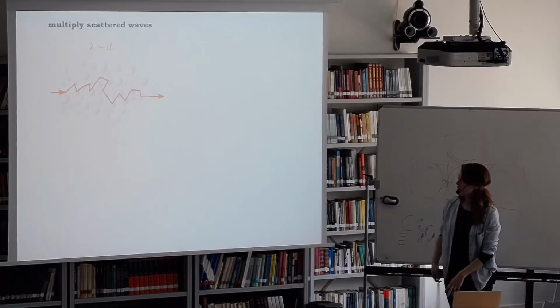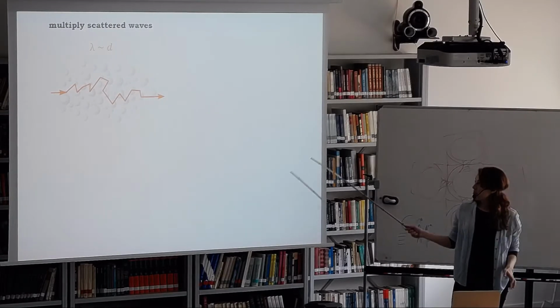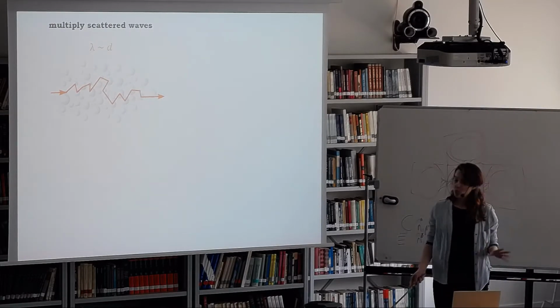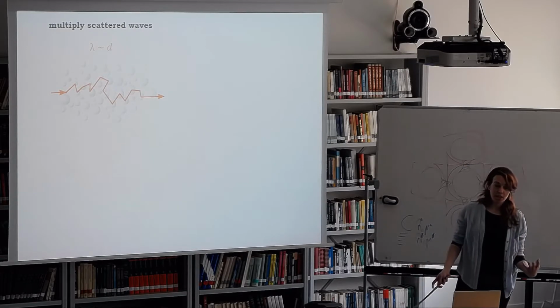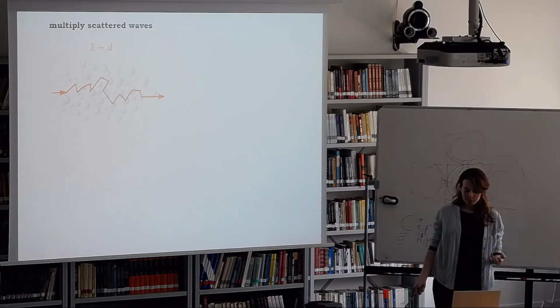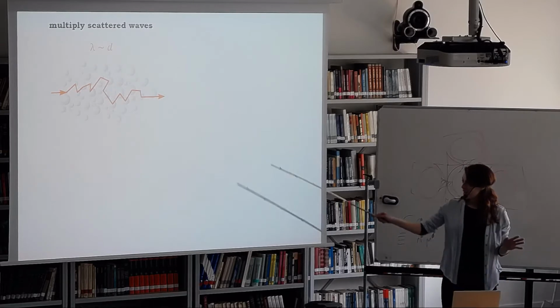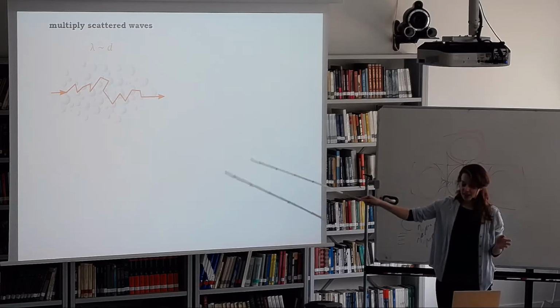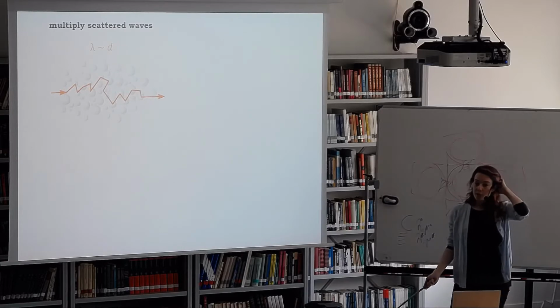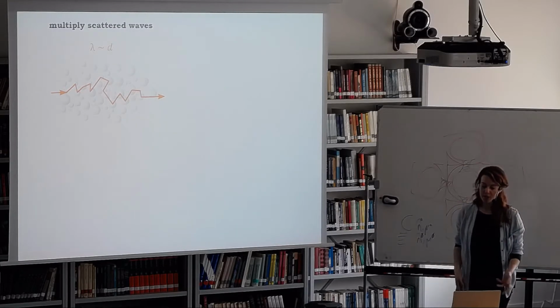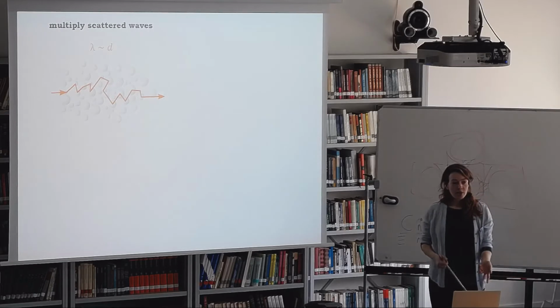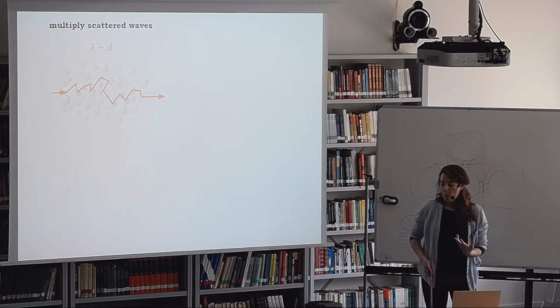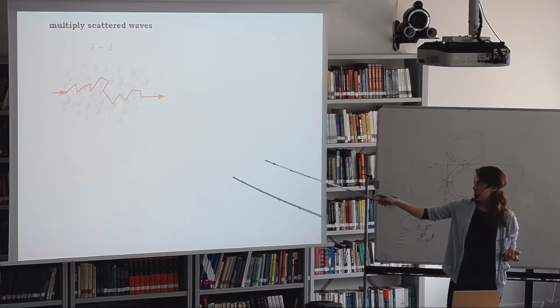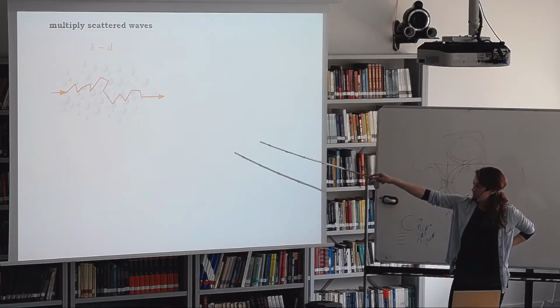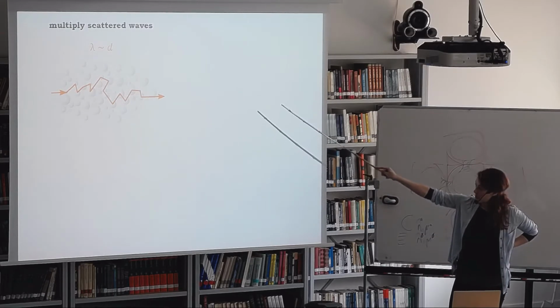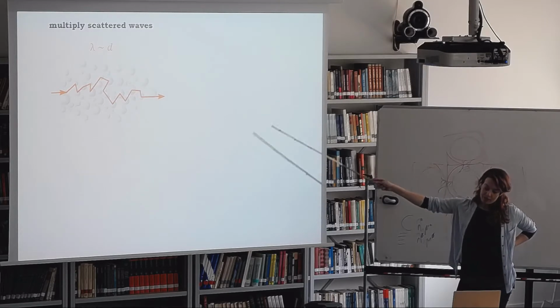Okay. So we're interested in this regime because when you have wavelength about the order of the scatterer size, you get multiple scattering of waves. So the waves are interacting with more than one scatterer inside the sample. Now, to be clear, they don't exactly jump from scatterer to scatterer as I've drawn here, but this is a super useful picture to describe this kind of wave propagation. In fact, wave behavior can be described surprisingly well by a model of a random walk in which a little walker comes, hits the first bead, and then takes a random direction until the next bead. Then he takes a random direction until the next bead, etc., etc.